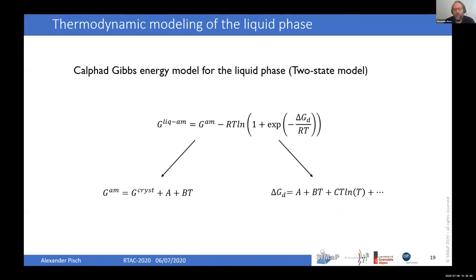And when it comes to the liquid phase in the Calphad community, which becomes more and more the standard is the so-called two-state model, where I consider that the liquid phase has two contributions, an amorphous phase and the liquid phase. And from this amorphous, solid-like phase, when I go up to high temperature, the liquid contribution takes over and becomes more important. And this is just a mathematical way of treating the description of the liquid phase. I will not go into details. I will show you some examples later in the presentation.